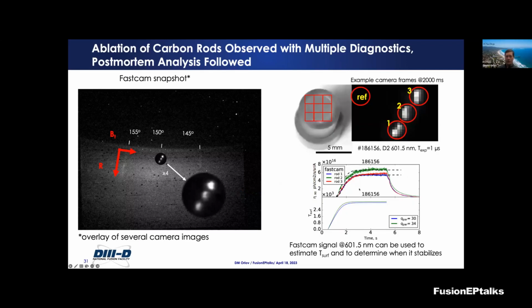And what we can do is convert the emission, the visible light emission from those rods, which is given here as a function of time, into surface temperature. If we assume some parallel Qs of 30, 34 in this case, we can estimate what the surface temperature was based on the visible imaging light that we're getting from those rods in the experiment.